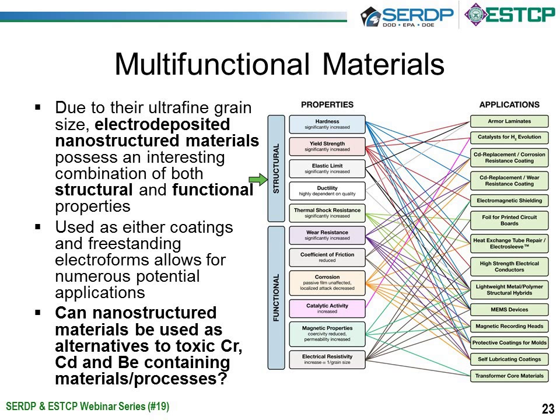An example of some of the functional properties is that with the decrease in grain size, you get excellent wear resistance. You get a lower coefficient of friction. You still get good corrosion resistance, which is largely determined by the composition, but you see a decrease in the localized corrosion attack. Since there's so many grain boundaries, the corrosion activity is spread evenly throughout the whole material and isn't focused on individual point sources as you see in conventional materials where you get severe intergranular attack. They also have interesting catalytic and magnetic properties.